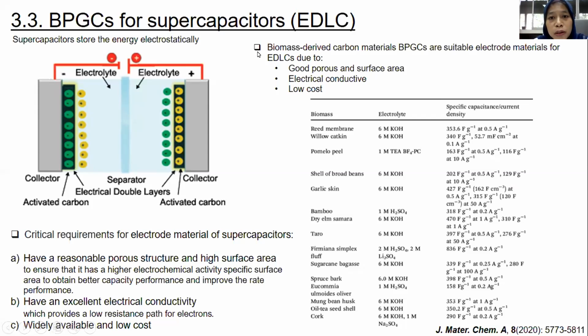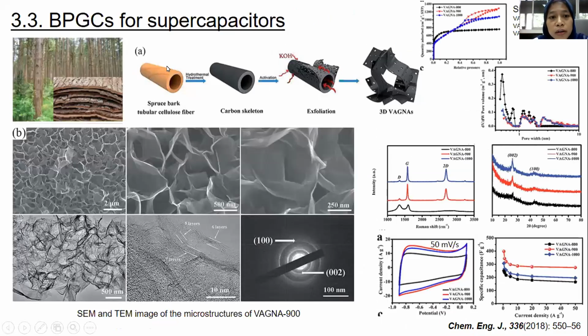And for supercapacitor, biomass is applied because of the good porous surface area, electric conductivity, and also low cost. The material as electrode material of supercapacitor has to have a reasonable porous structure and high surface area, have excellent electrical conductivity, and also be widely available and low cost. And this is an example of research about the application of BPGCs as supercapacitor. We can see from spruce bark and tubular cellulose fiber that it shows good performance and stability of the supercapacitor.